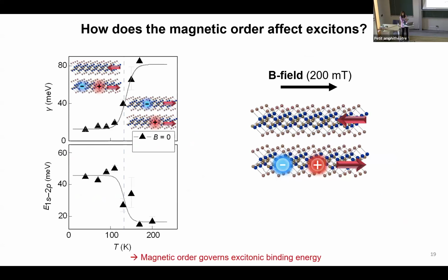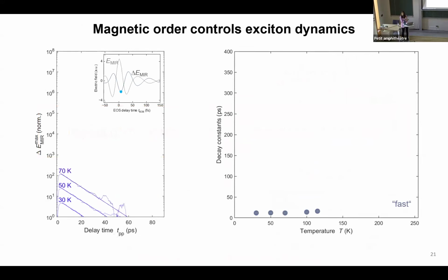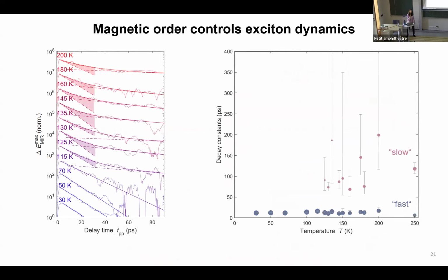Yeah. So since you're generating these excitons with photoexcitation, do you have a way of estimating how many you have? I mean, what is the density of excitons in the system? Yeah, so I don't remember the exact numbers, but we can calculate it. We simply use a transfer matrix formalism to calculate the absorption of our flake, which is exfoliated on, for instance, a diamond substrate. And then with the fluence of our pulse, we can calculate it, and we were below the Mott density in our system. So we do not generate free electron and hole pairs. We do not ionize the excitons, if you want. And there are not so many that they start interacting with one another. Exactly. So we are far below the Mott density.